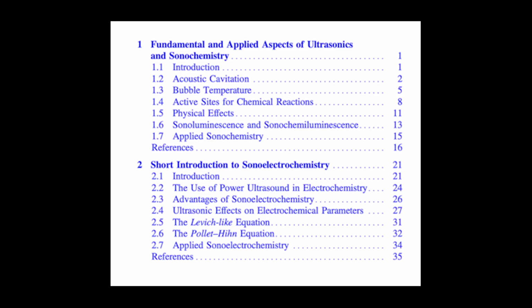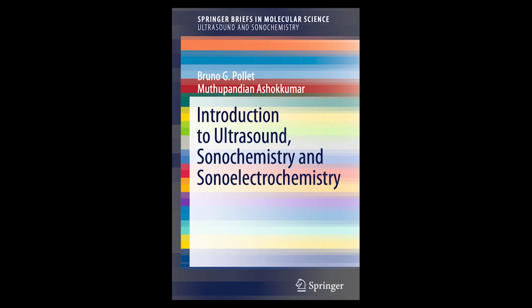The second zone is the thin liquid layer right at the interface, the shell of liquid immediately surrounding the collapsing gas cavity. This layer gets incredibly hot too, maybe around 1900 K, but it's different. It contains vaporized solvent, but also potentially non-volatile solutes that were near the bubble surface. So a slightly cooler but still very hot interface region.